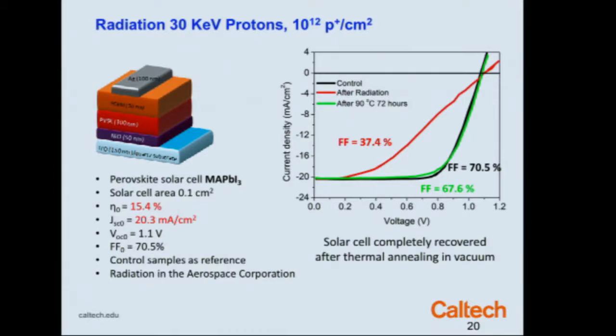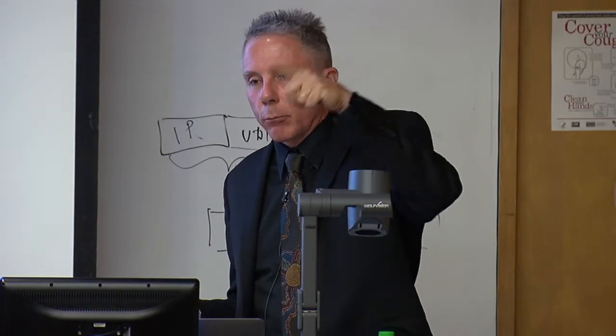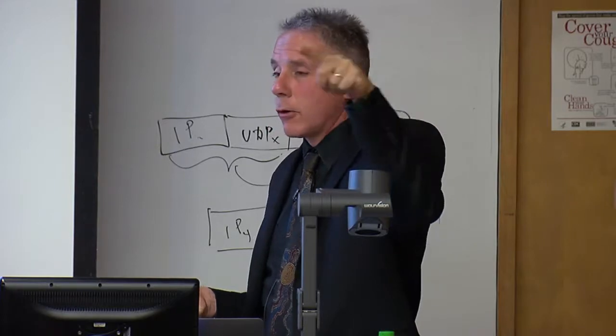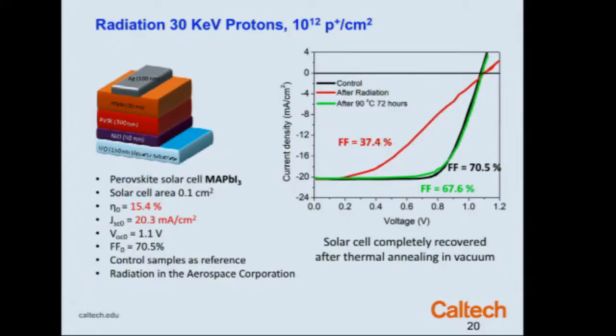Nonetheless, upon annealing at 90 degrees C, and by the way, every time a satellite goes from the dark side of the Earth to the bright side of the Earth, it goes from roughly minus 50 to 100 degrees C or so, so you could think about a low Earth orbit as an anneal cycle. This solar cell recovers its performance completely. So this is a remarkable thing. So we're collecting now many gigabytes of data, not as many terabytes as Roger would hope us to collect, but we're collecting a lot of data. In fact, we look forward to working with his group on the data analytics.